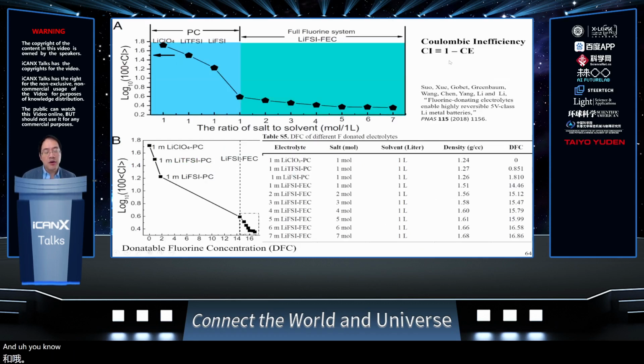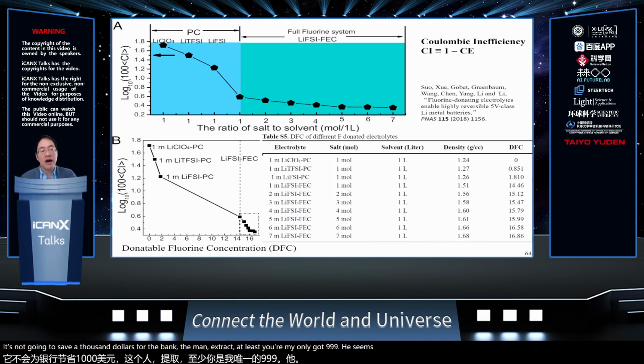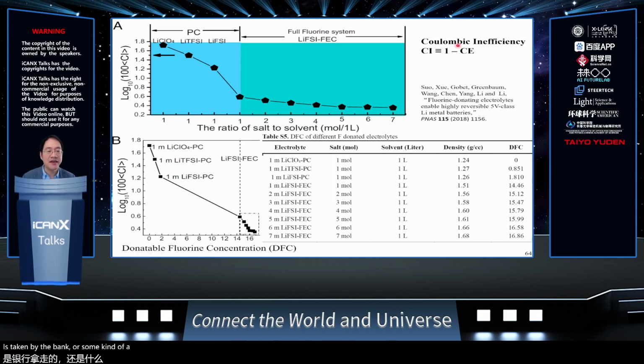And in our group, we are looking at liquid electrolytes. So one thing that we pay close attention to is this so-called Coulombic inefficiency, which is 1 minus the Coulombic efficiency. This is, let's say, if I deposit 1,000 lithium atoms to the graphite anode, it's like I save $1,000 to the bank. But when I extract the lithium, I only get 999 lithium out because one is taken by the bank as some kind of a processing fee and is stuck on the anode, is deactivated. And so this Coulombic inefficiency is, for a lot of batteries, inversely proportional to the cycle life. So how many cycles the battery can store energy and discharge.